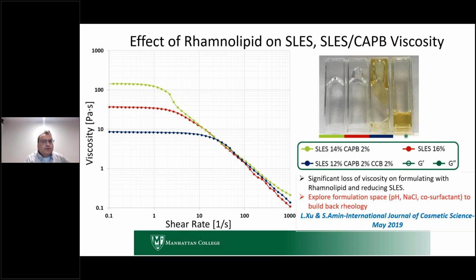So if you look here, the red line is basically just SLES at 16 weight%. When you add CAPB to it, because of those favorable electrostatic interactions, you actually build up further viscosity because of elongation of the worm-like micelle. So you get to that green curve over there, and that green curve is basically 14% SLES and 2% CAPB. Now, if I start to replace that 2% CAPB by 2% of rhamnolipid, you see the viscosity drops drastically, right? So it comes down to that blue line here.